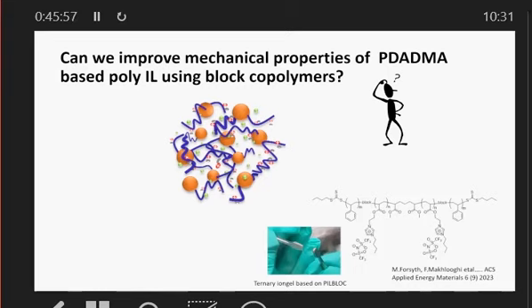So it's not ideal, whereas the DADMA seems to be much more stable at the higher voltages, at the more positive voltages. Whilst this works nicely, and CSIRO are currently doing a startup to try and commercialize this material, it's not ideal on the high voltage cathodes. So can we use the same technique to try and make a nice material with the DADMA?